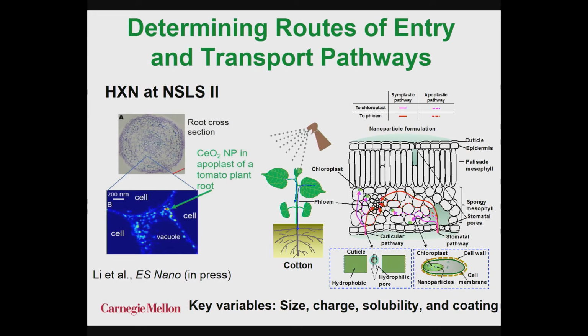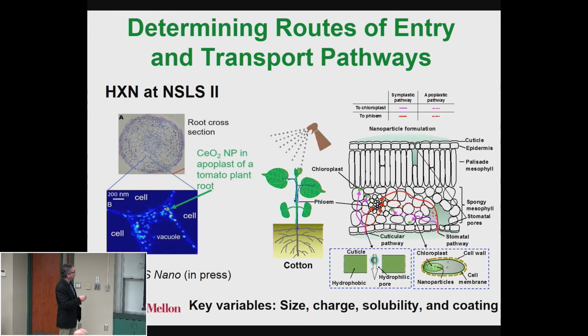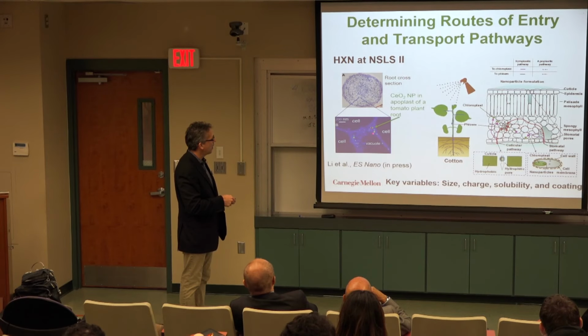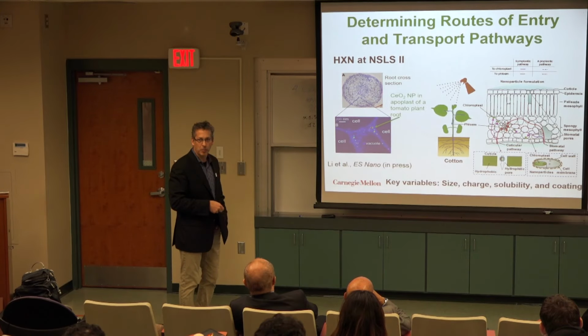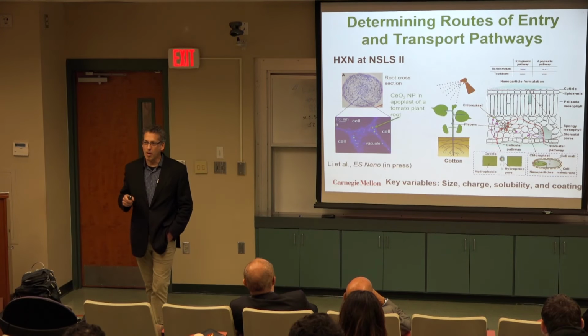And what we did at NSLS-II on this line called HXN, which is a microprobe mapping line that can also do tomography. This microprobe can focus down to 10 nanometers. So this is about 20 nanometer resolution. And what you're seeing here is cerium oxide nanoparticles in the apoplastic space. That's a cell, that's a cell, that's a cell. It's in the apoplastic space in a root. So we know with certainty, we never found anything in the cells themselves. So we know for root transport, it's apoplastic transport of these particles through the roots.